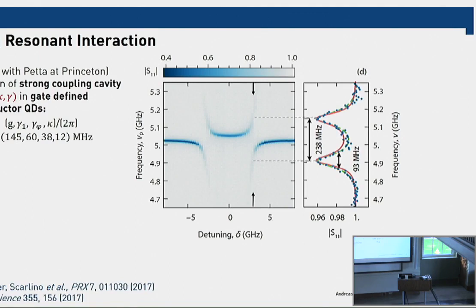And the coupling strength 2G here was about 240 megahertz, and the line width was about 90 megahertz or so. So that just barely made it, and now you could ask, okay, why did it make it? And it's exactly this factor of 5 or so that we got from this trick with this impedance that moved this from not working to be in the strong coupling limit.